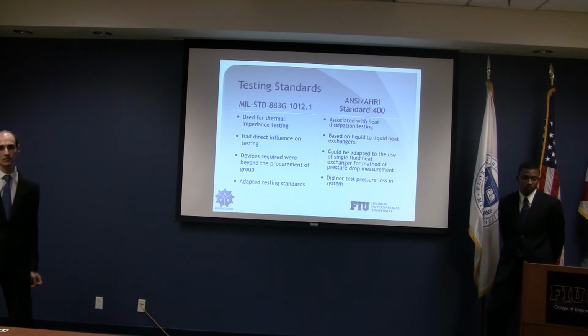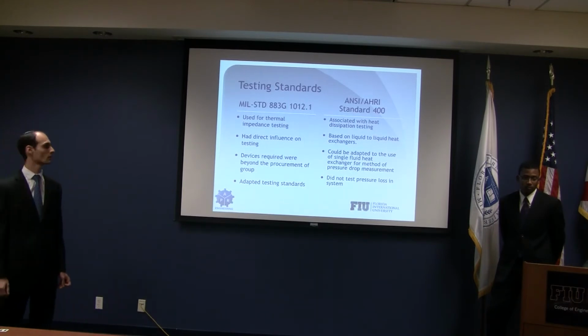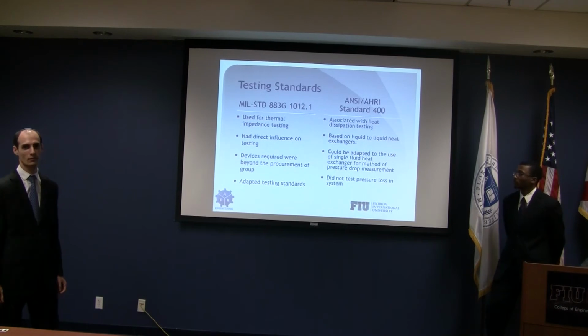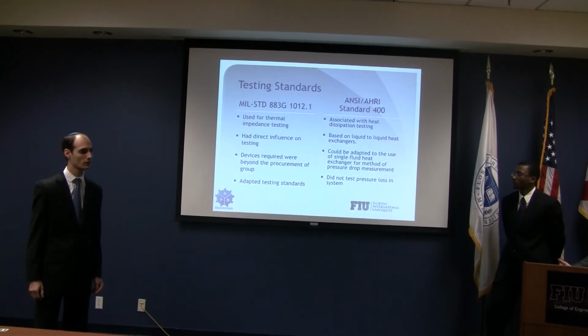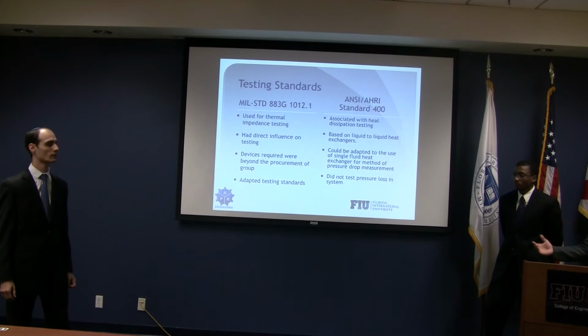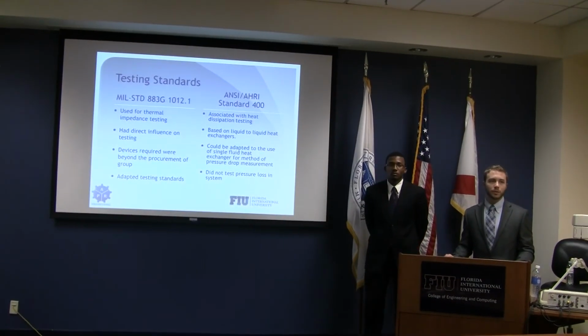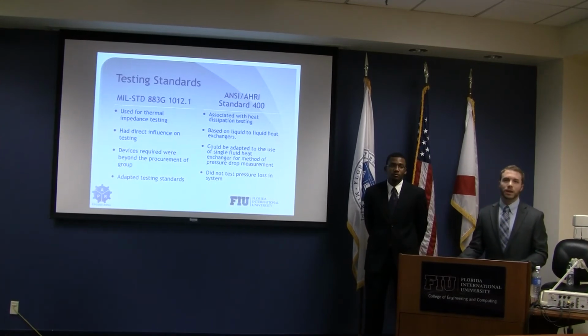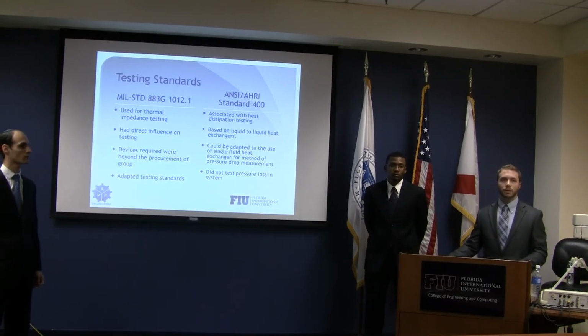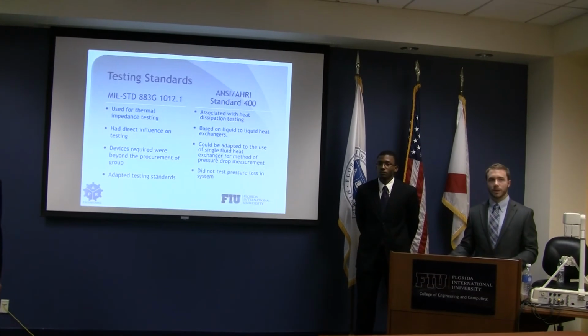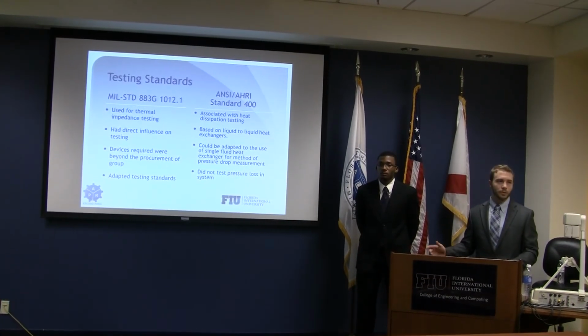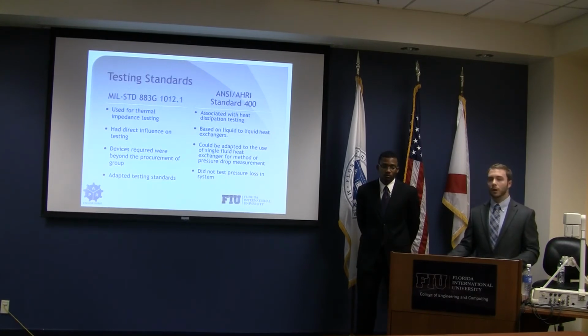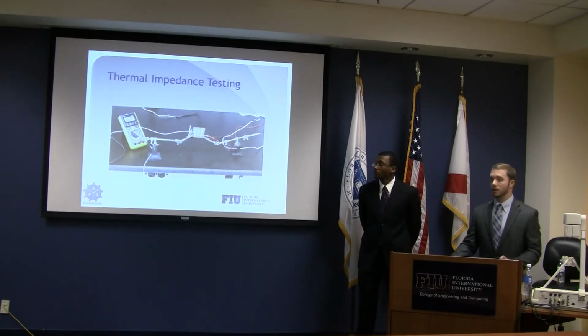The other standard that we came across is the ANSI AHRI 400. And what this standard is for is liquid-to-liquid heat exchangers. It could be adapted for a single-phase heat exchanger, which is what we have, but it was particularly for pressure losses associated with the device. So essentially what it tells you is that if a manufacturer prescribes a pressure loss, the customer can expect to see within 10% of the prescribed pressure loss. As we did not use pressure losses or test for it in this project, we didn't actually use this standard, but it is applicable. So this was the test that we had for thermal impedance.